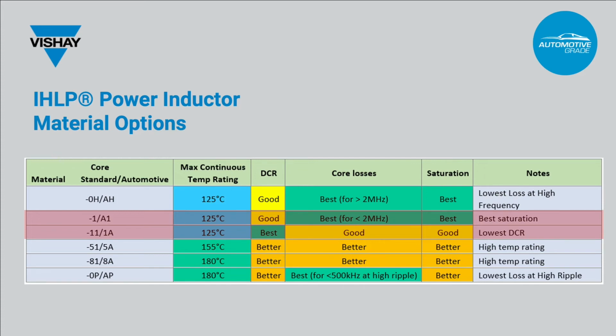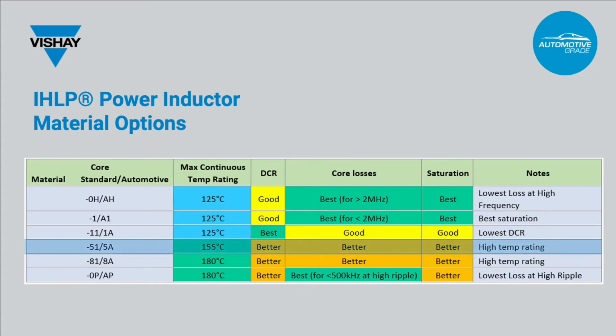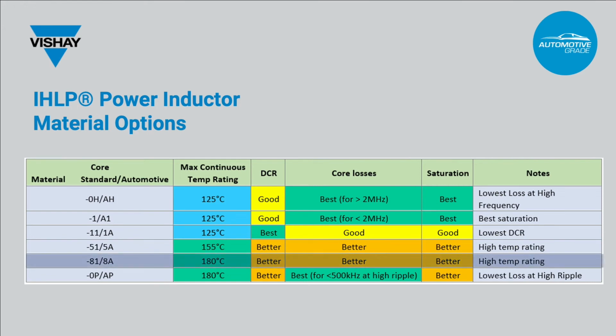are still reasonable. In the years since the inception of the IHLP, there has been continuous improvement in the iron powder technology in terms of temperature and frequency response. There are now two more options with regard to the maximum continuous operating temperature. The -5A material can be used up to 155 C, and the -8A material can be used up to 180 C. Both of these materials have been optimized in terms of the core losses and DC resistance, so the resulting frequency response and DC losses are a good compromise between the -A1 and the -1A materials.